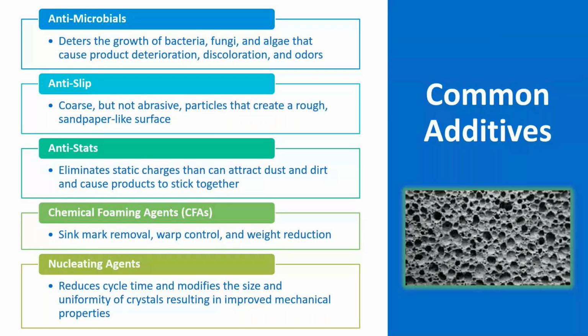Essentially what it does is it creates those air pockets in the material to help with sink mark removal, warp control, or weight reduction. So if you're having issues with sinks, maybe the part happened to be designed a little too thick in a certain area and we're not able to fill out the part without creating a sink there, a chemical foaming agent could help. So there's a few reasons you might use those.